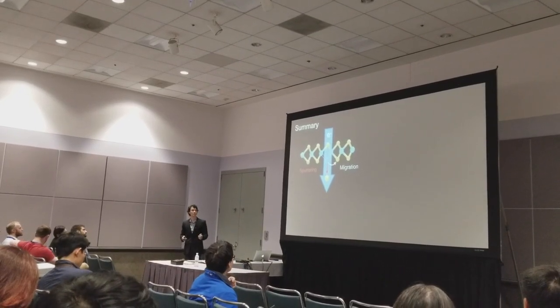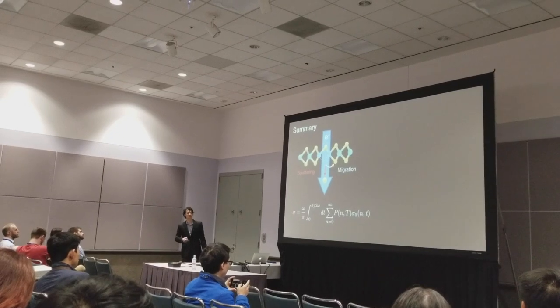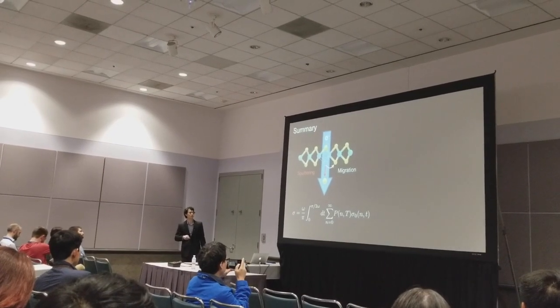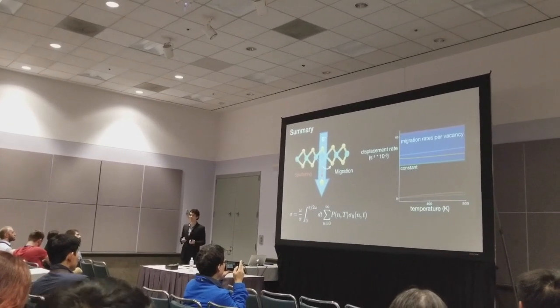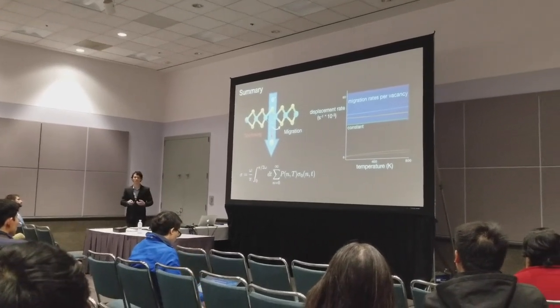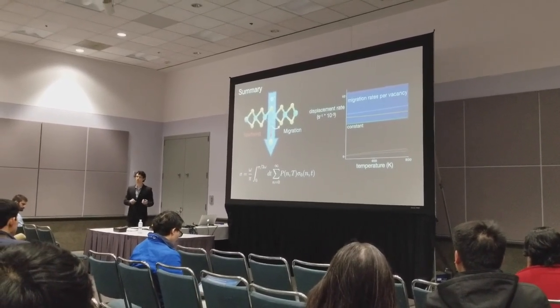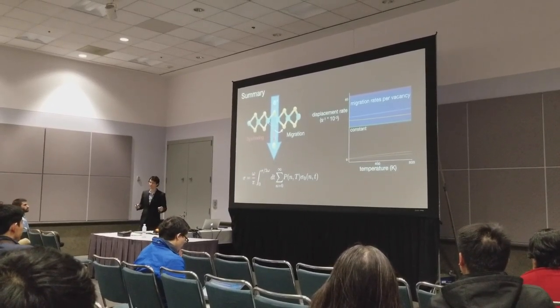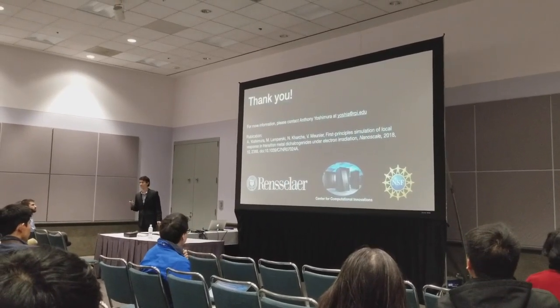To summarize: we identified two fundamental displacement processes — migration and sputtering. We can determine their rates by plugging displacement thresholds into our temperature-dependent cross-section. This shows that at just the right TEM energy and at low temperature, we can induce migrations without significant sputtering. This should allow for the controlled manipulation of irradiated TMDs without the risk of significant collateral damage. With that, I'd like to thank you for your attention and I'm happy to take questions.